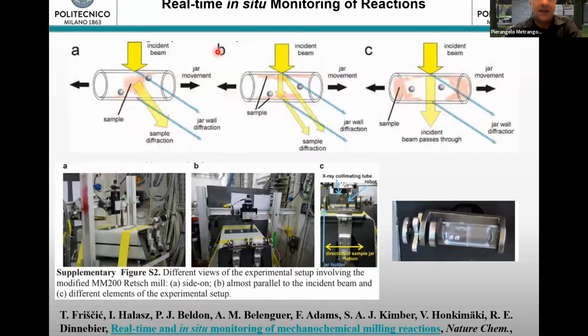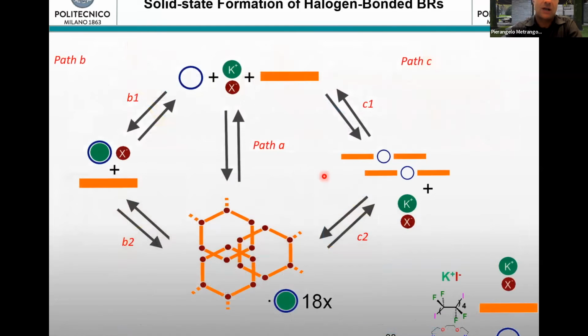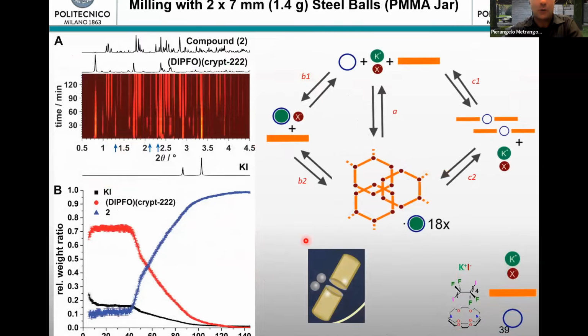And this was very nice because we wanted to see whether this very complex Borromean structure forms fully in the solid state. So we made these experiments with a jar and ball milling under synchrotron radiation, and we could discover a very nice story. Actually, this three-component system in the solid state might get to the interpenetrated system or to the non-interpenetrated one. And if we use only two small balls, it is very easy to see that you get the non-interpenetrated system in a very high yield, directly in the solid state.